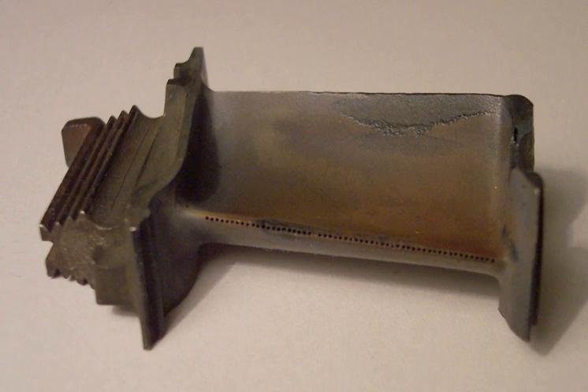The primary strategy used to limit these deleterious processes is called selective oxidation. Simply, the alloy is designed such that the ratio of alloying elements promotes formation of a specific oxide phase that can then act as a barrier to further oxidation. Most commonly, aluminum and chromium are used in this role, because they form relatively thin and continuous oxide layers of alumina, aluminium oxide, and chromia, Cr2O3, respectively. Furthermore, they possess low oxygen diffusivities, effectively halting further oxidation beneath this layer. In the ideal case, oxidation proceeds through two stages. First, transient oxidation involves the conversion of various elements, especially the majority elements, e.g. nickel or cobalt. Transient oxidation proceeds until the selective oxidation of the sacrificial element forms a complete barrier layer.